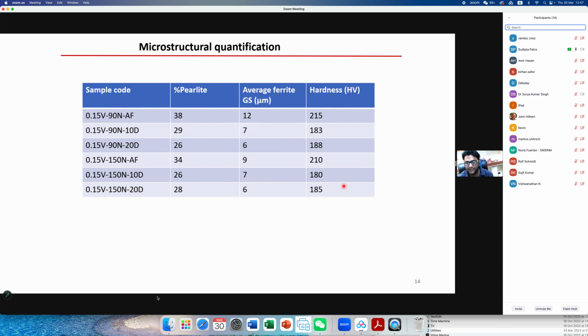But this is the hardness value. You can see that in case of 90 and as-forged, we are getting the highest hardness value, 215 HV, and as we are normalizing the steel, at least 30 HV hardness is dropping in both the cases almost.